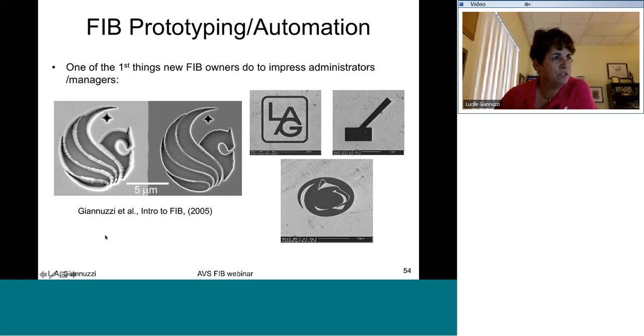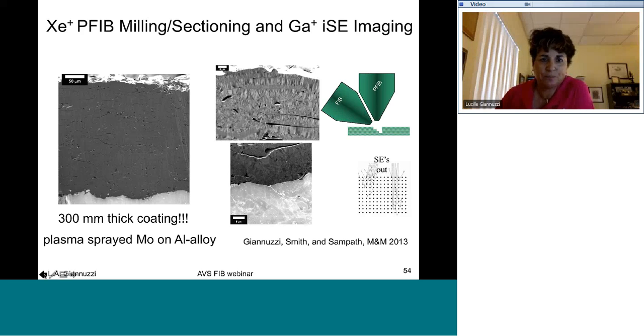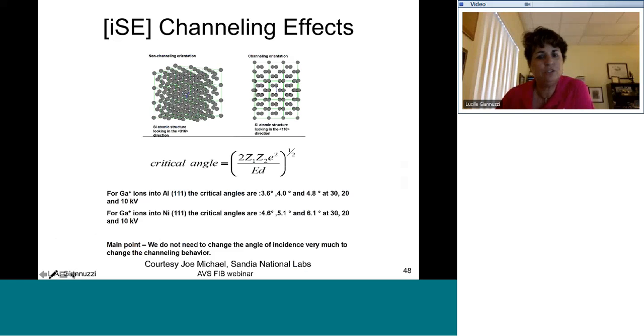Someone asked the question: in practical applications, do you calculate these angles before imaging or just rock the sample until the contrast is good? So in a practical application, you can calculate those angles for any material. If we go back to the ion channeling contrast in general, this equation you can calculate for any material, but typically it's going to be in the sub 10, less than 10 range.